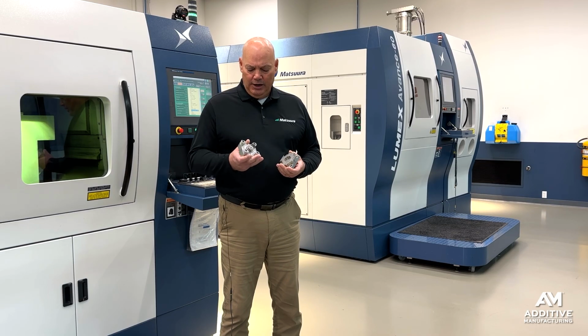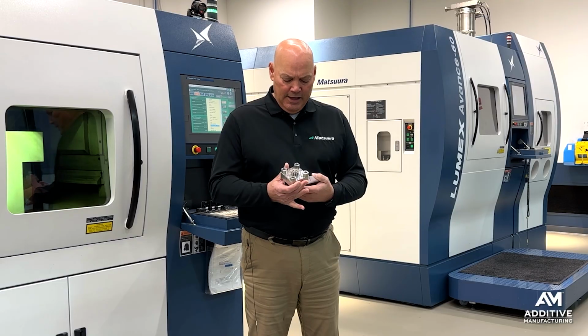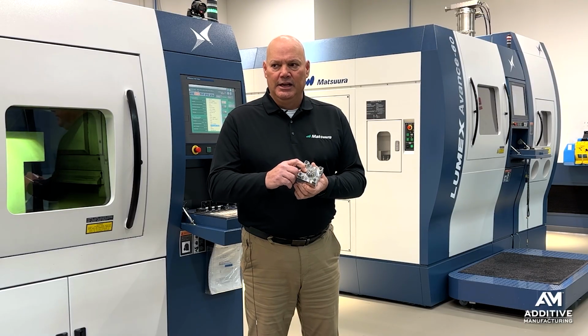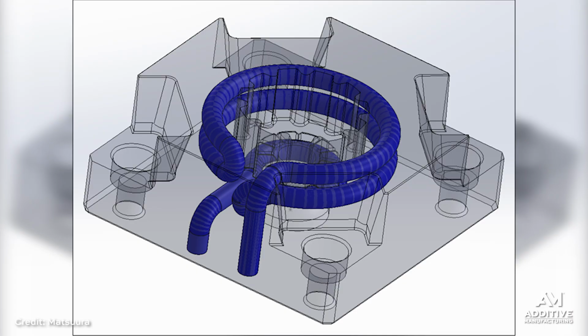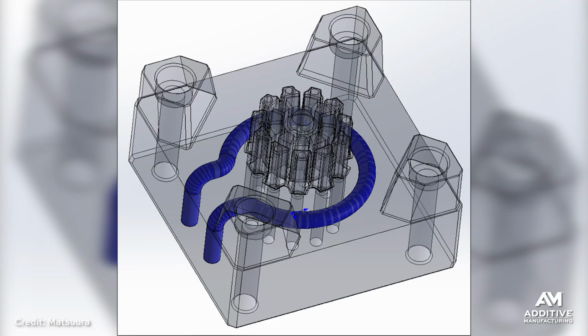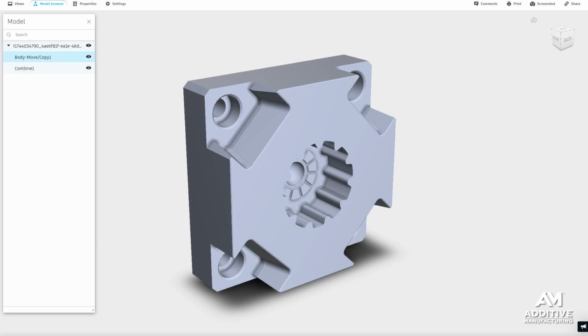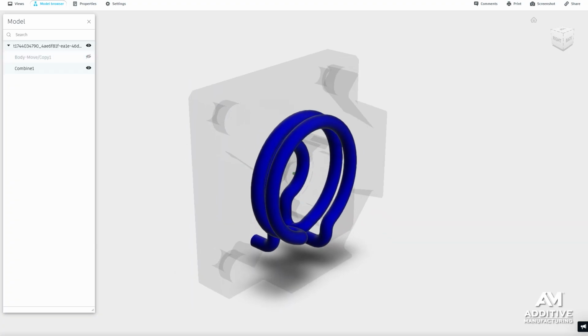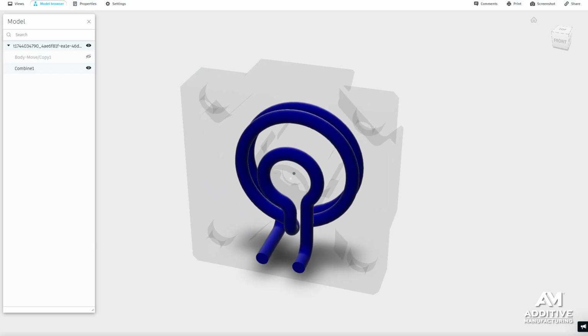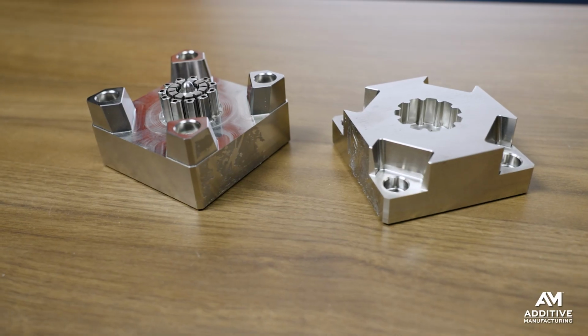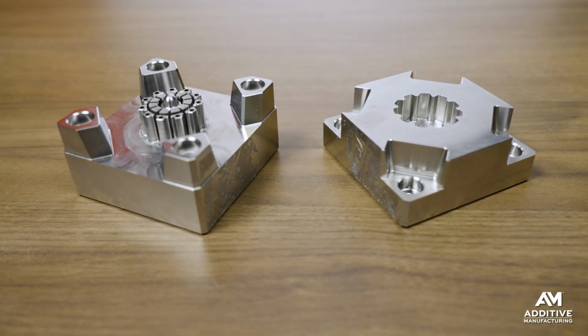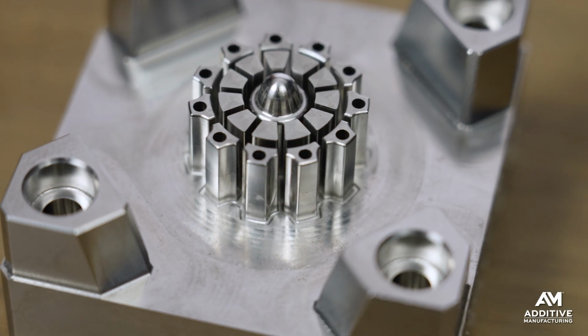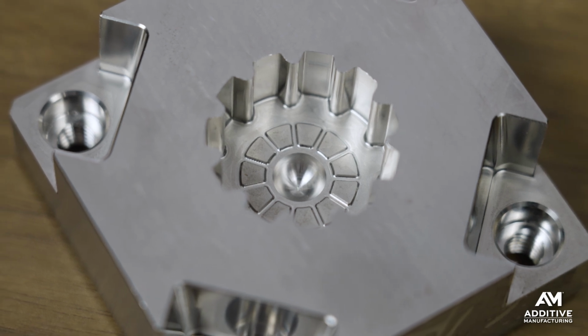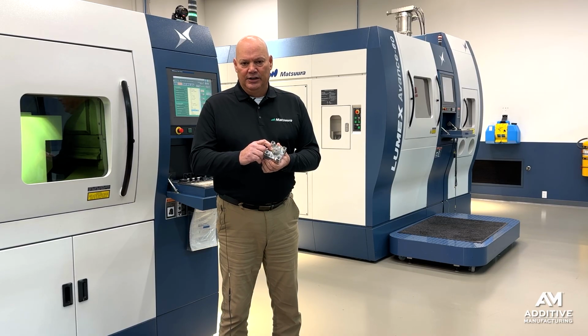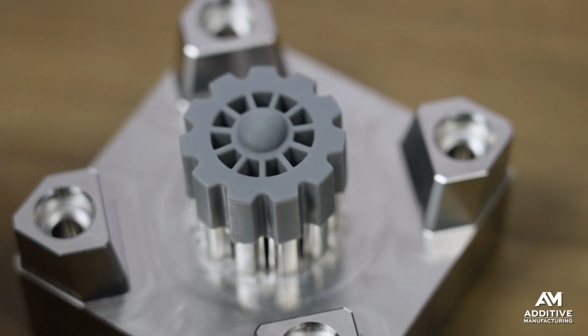So we worked with the customer, developed a conformal cooling path, and then integrated porous venting into the bottom of these ribs. Conformal cooling. Channels 3D printed on the inside of the form to follow the geometry, bring the cooling closer to the surface, closer to the plastic so that the plastic cools faster, solidifies faster. And porous venting. Porosity 3D printed into the steel so that the tool is every bit as effective at holding and containing the plastic, but air passes through. So there's actually a porous material that's sintered and machined at the bottom of these ribs.